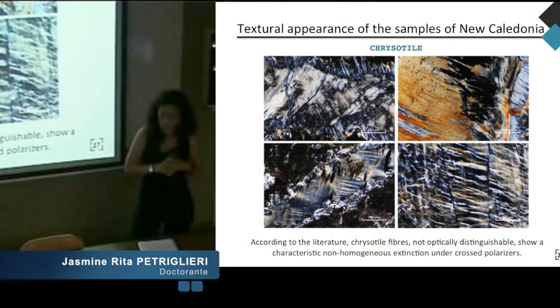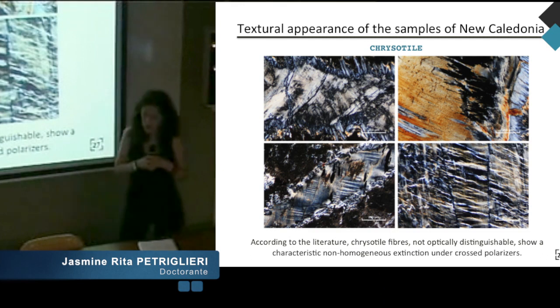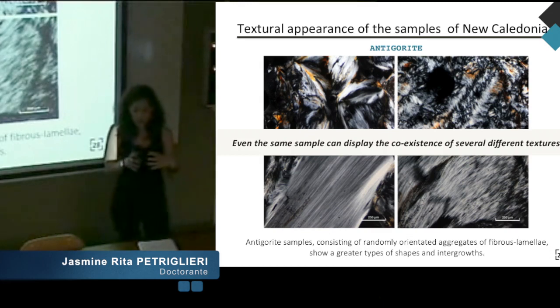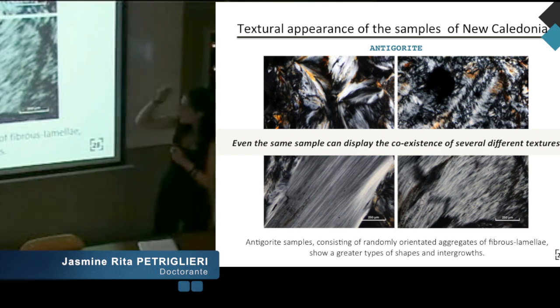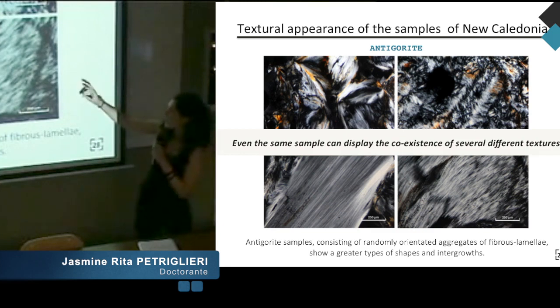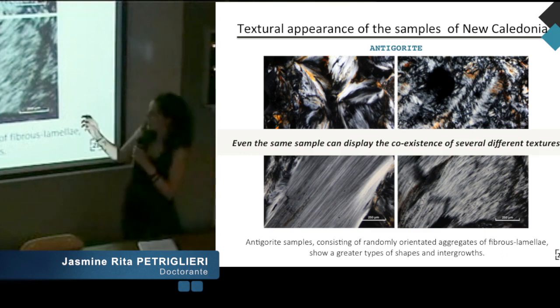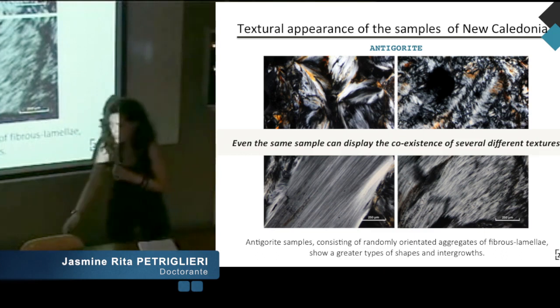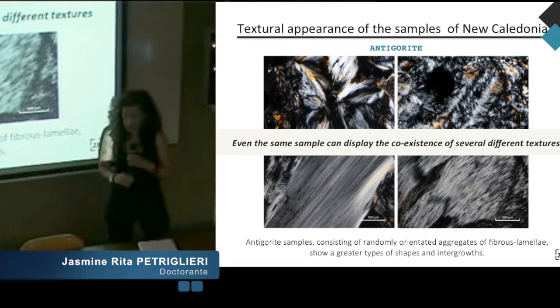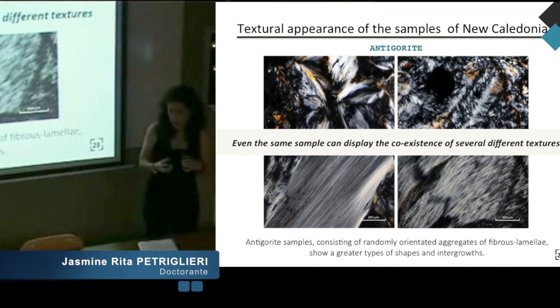Concerning chrysotile, the optical microscope image shows the typical characteristics found in the literature. On the contrary, for antigorite samples in New Caledonia — consisting of randomly-oriented aggregates of fibrous lamellae — we observe a greater variety of shapes and intergrowths. We can observe four kinds of textures: from left to right, star and fan-formed aggregates, the most typical interpenetrating textures, lath-shaped lamellae, and fibrous blades. All four textures were found in the same sample, meaning that several kinds of textures can co-exist.